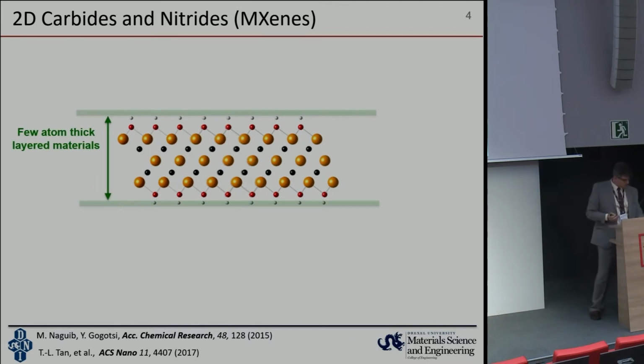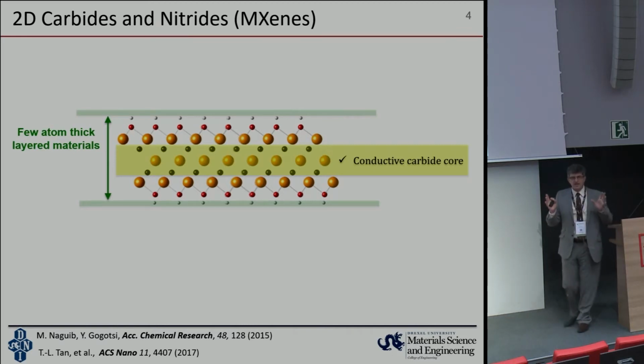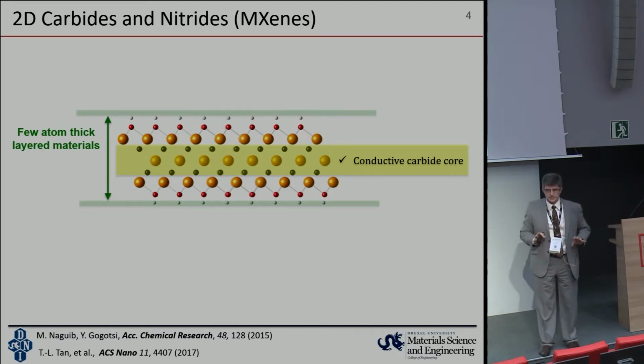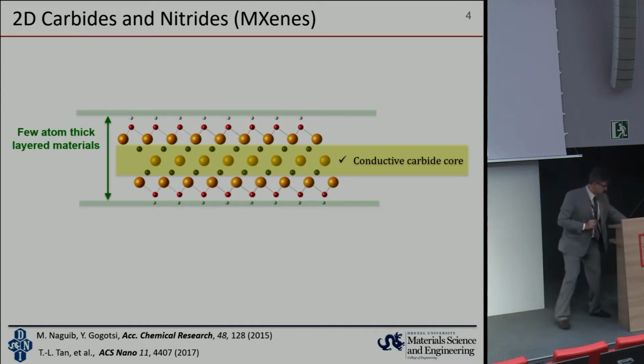Those layers are just a few atoms thin, just like pretty much any other 2D material. But there is a very important difference that makes them different from the great majority of other materials in the 2D state. They have a truly conducting metallic core, at least most of them. Some of them are semiconductors. There are many semiconducting 2D materials. Graphene, which everyone praises for high conductivity, is really a zero band gap semiconductor with a low concentration of carriers. Many of these materials are true metals with a high density of states at the Fermi level and with a high concentration of carriers.